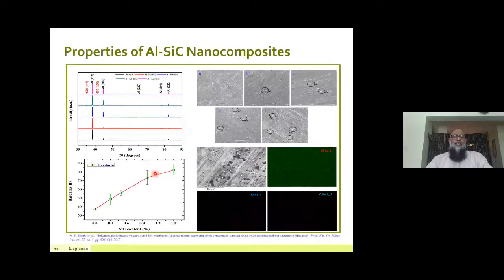Let me start with the aluminum silicon carbide nanocomposites. As I have said, we started with the aluminum powder and silicon carbide powder. They were mixed together and sintered. And this is the XRD spectra of the various compositions that were produced. This is the pure aluminum, and then 0.3% silicon carbide, 0.5%, 1% and 1.5% silicon carbide.